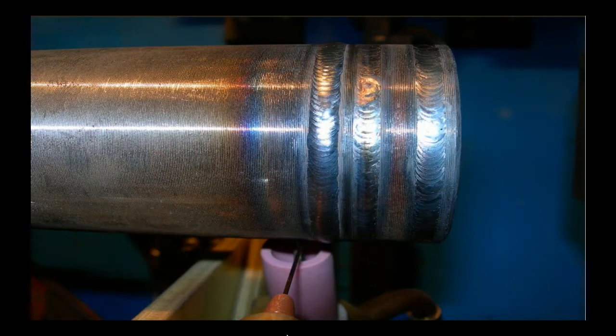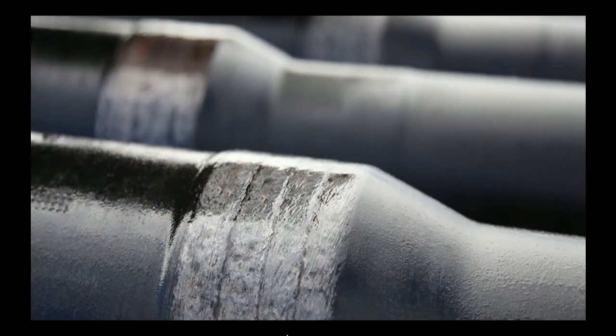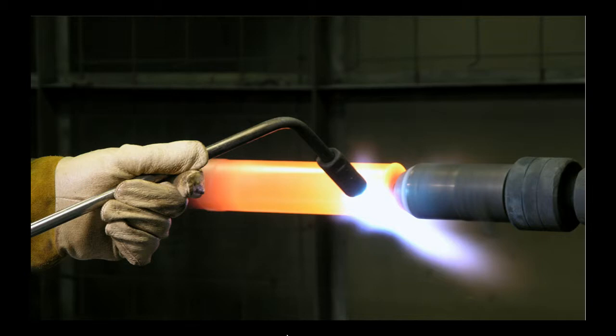Copper melts at 1981 degrees and silver at 1762 degrees Fahrenheit. Yet if a piece of copper foil is sandwiched between two sections of silver, it will alloy with the silver at 1450 degrees Fahrenheit. See Figure 2. The alloy is formed at the interface of the joint and is therefore called a surface alloy. The degree of alloying depends upon the affinity and diffusibility one metal has for another, the wetting properties, and the composition of the chemicals when a flux is used.